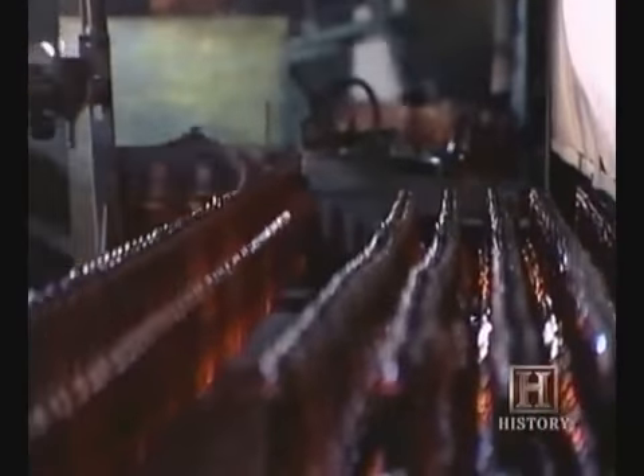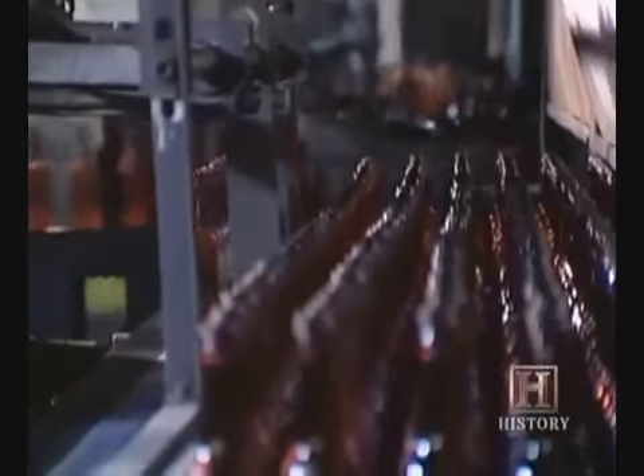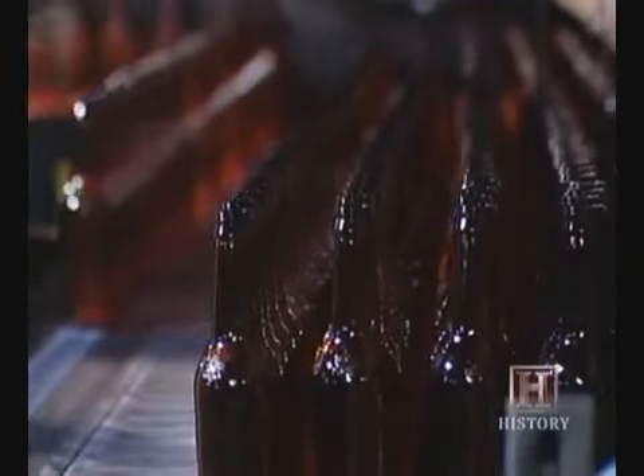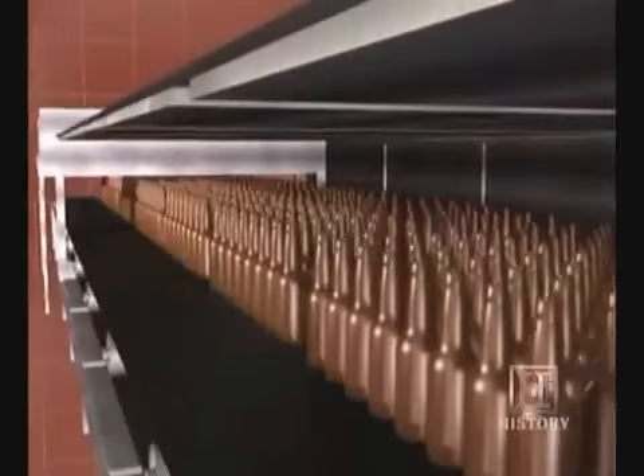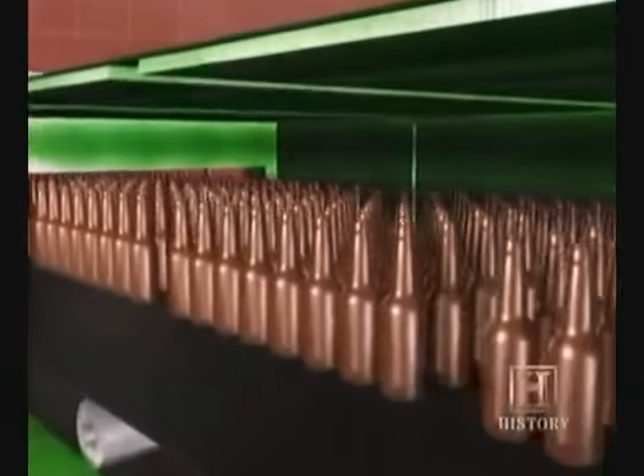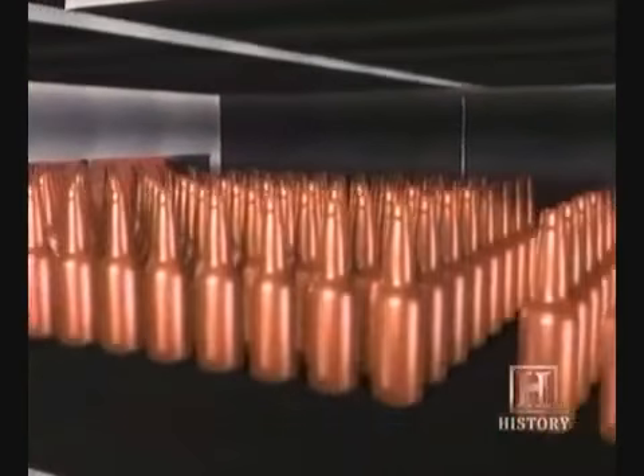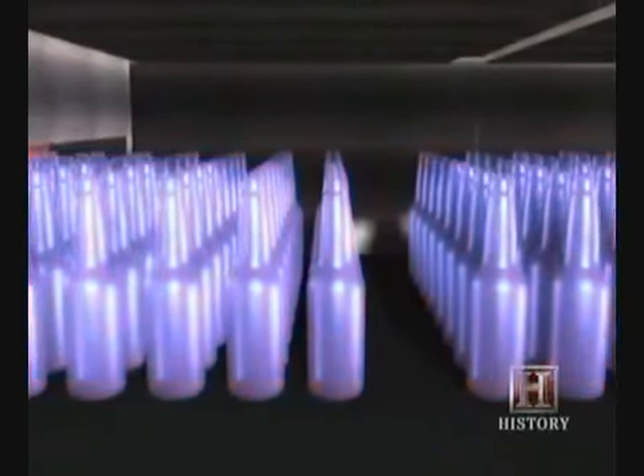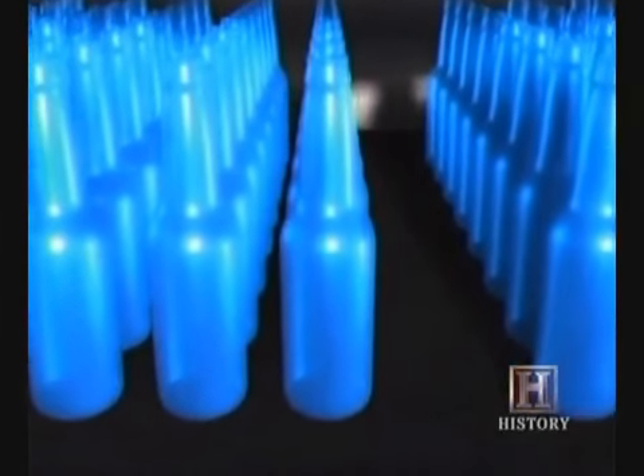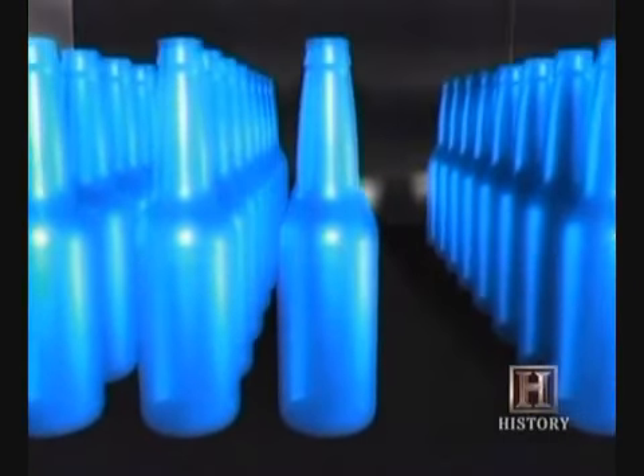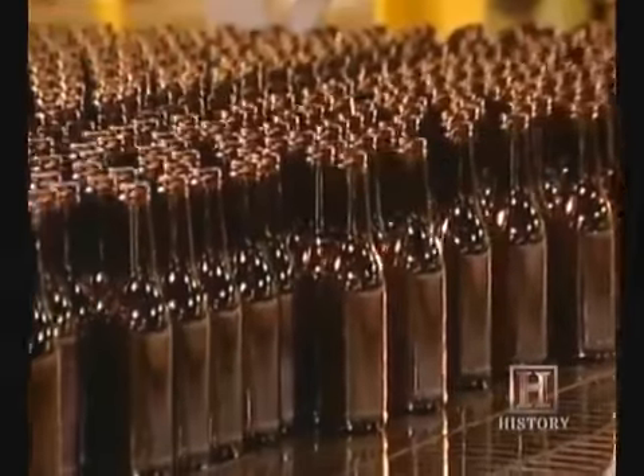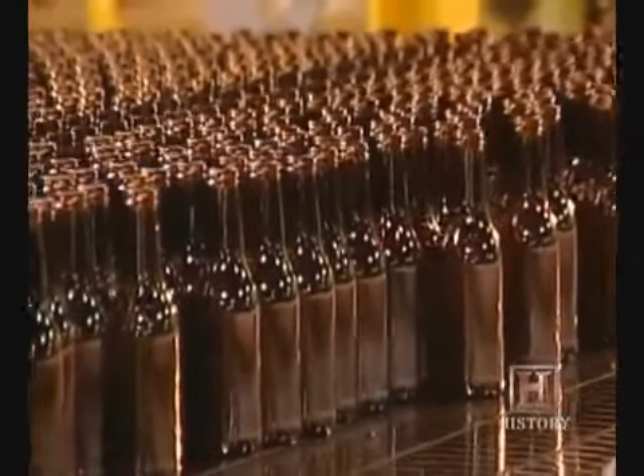The extreme change in temperature can cause stress in the bottles if they're not cooled properly. Therefore, the formed containers are loaded into an annealing leer, where their temperature is raised to 1,000 degrees, then reduced gradually to below 200 degrees. This reheating and slow cooling eliminates the stress in the containers, making them stronger and more shock resistant.